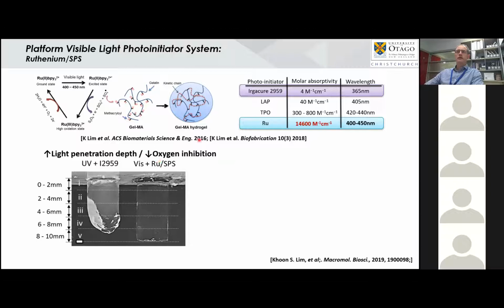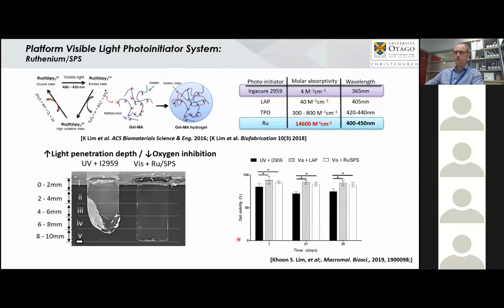We recognize that with visible light, particularly the ruthenium, there is extremely high molar absorptivity, and so very low concentrations of the ruthenium photoinitiator can allow quite complete cross-linking. Using visible light, you also get quite good penetration depth compared to potentially UV and Irgacure.